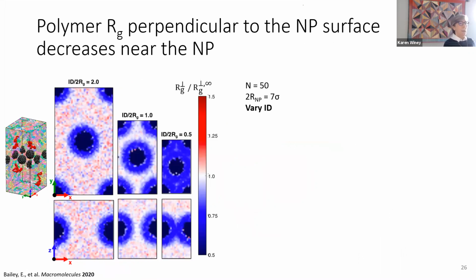Okay, so these are color maps, where we're either looking at the XY plane, which is the long side here, or we're looking at a cut through the center, so either the XY plane or the XZ plane. And the blue data, again, we're looking at the radius of gyration perpendicular to the surface versus what it is in the bulk. And the blue indicates that things are a little flattened. And this is with an athermal surface, so the polymer-polymer interaction is the same as the polymer particle interaction. And so even in that case, the chains are a little bit squashed onto the particle surface.